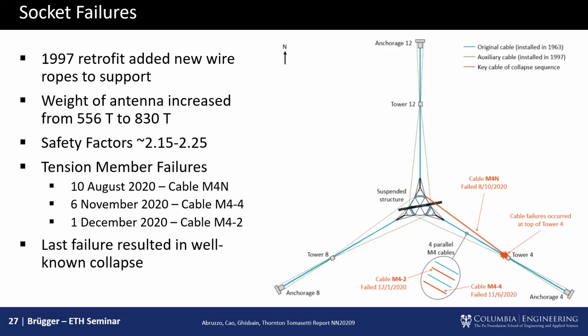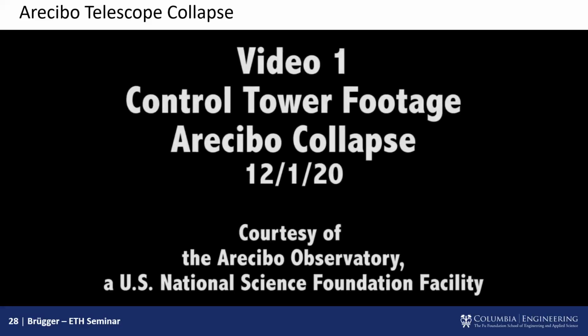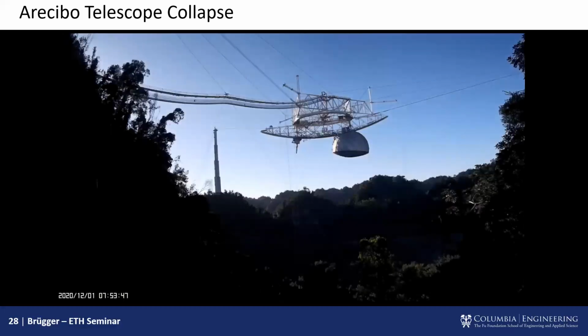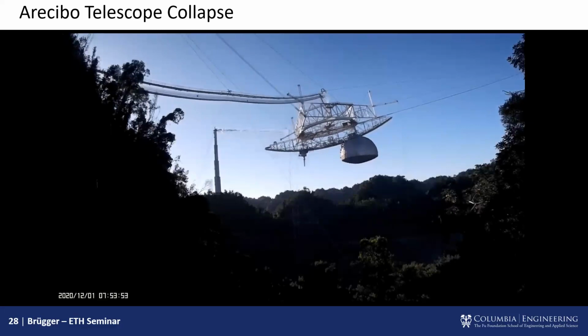And then in August 2020, of course, they had their first failure. And this was at this point already a very old and worn facility. And at that point, the forensic engineer, Thornton Tomasetti, was brought on site, and they started to do a design for the replacement. But as that happened, the next wire, just a few months later, M4-4 failed, and then M4-2 failed shortly thereafter, causing the catastrophic collapse of the telescope. Now, luckily, because there were already previous failures, the site was fully evacuated, and there were cameras.